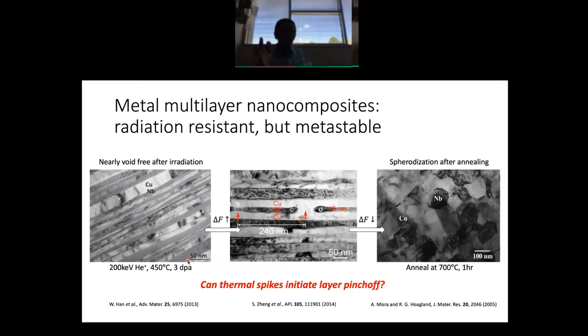But because this is not pure copper and pure niobium, this is a composite, okay? The defects that would have been generated by this radiation were almost entirely absorbed and recombined at the interfaces. And so this micrograph that you see here is basically void-free, right? That's just a signature of the radiation resistance of these materials. So these materials are radiation resistant, so that's good. One of the drawbacks is that they are metastable. So the interfaces between the copper and the niobium are very, very sharp,